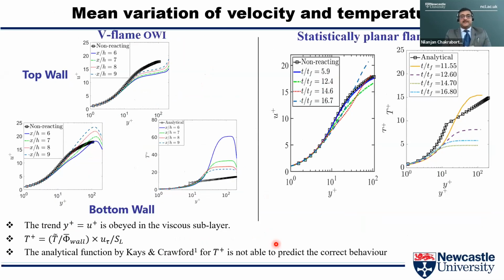So what happens to the textbook material? If we look at the log law, it really falls down for flame wall interaction. This relation for the viscous sublayer still holds. What happens for the thermal boundary layer? The well-known relation by Kays and Crawford falls miserably here. So effectively, all the textbook materials in the heat transfer literature are invalid in the case of flame wall interaction.